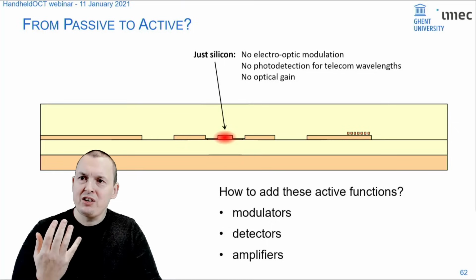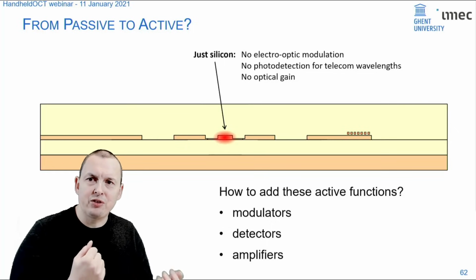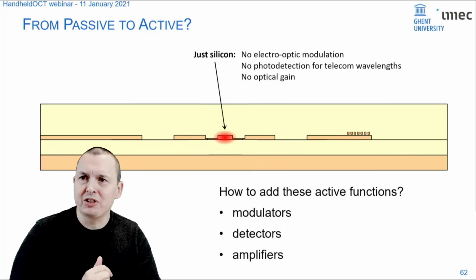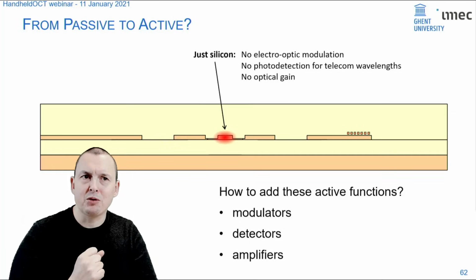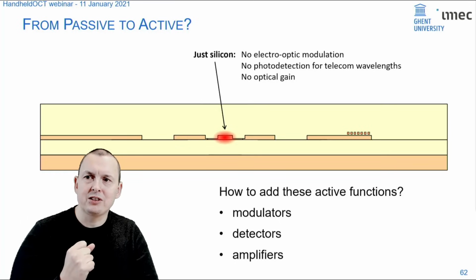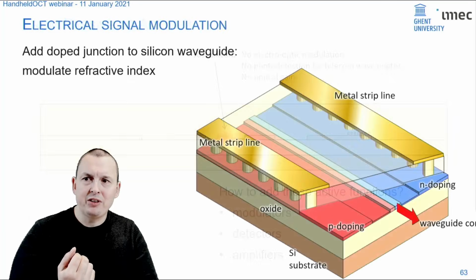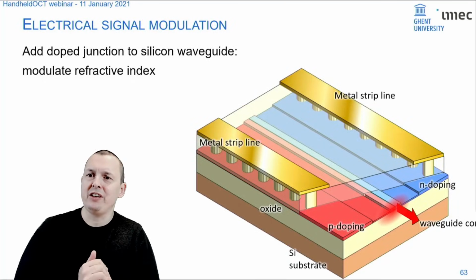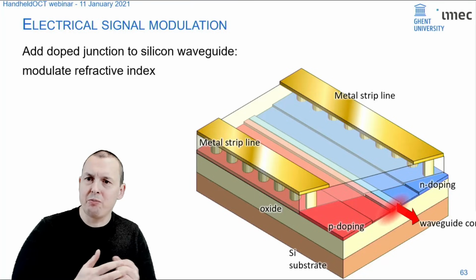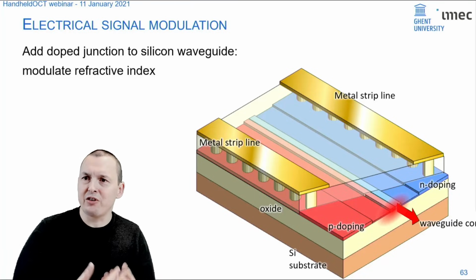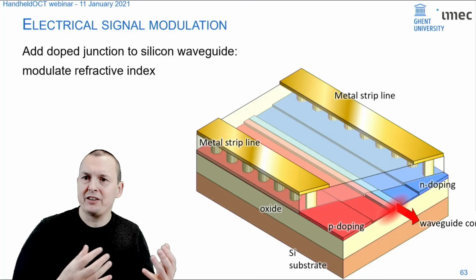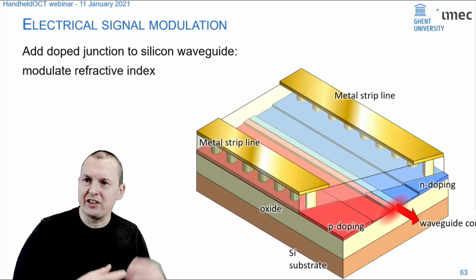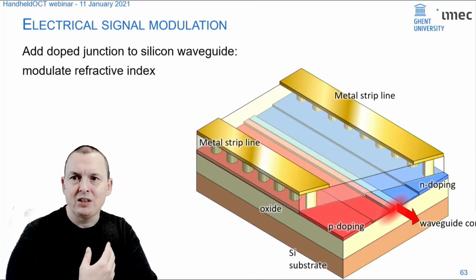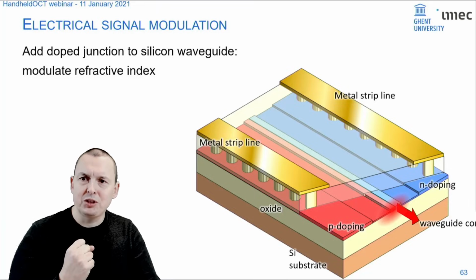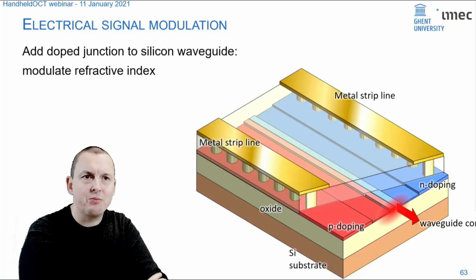Well, for the modulation, people in silicon photonics came up with a clever trick that bypassed the problem of silicon as a not really good electro-optic material. They basically used the presence of carriers in silicon. And the presence of electrons and holes affects the optical behavior. So what they did, using all the tricks that were already developed for electrical engineering, is to make PN junctions, like diodes, inside your waveguide. And by applying a voltage over that diode, you can pull out the carriers or you can inject carriers there, which modulates the refractive index. Note that that also modulates the loss, because these carriers can introduce quite some optical losses.